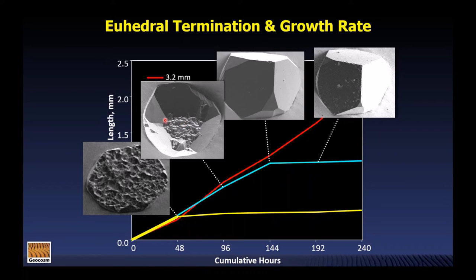On the other hand, on these euhedral faces, these faces represent minima in terms of the density of unsatisfied atomic bonds. So although a given unsatisfied bond here would be growing at the same rate as one here, because we have such a higher density here, we grow the crystal faster. And so this is what's controlling the difference in the rate of growth along the c-axis on this type of surface compared to these pyramidal faces on the quartz crystal.